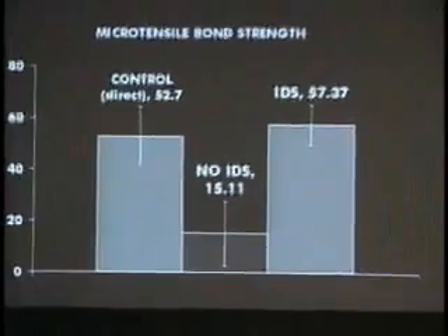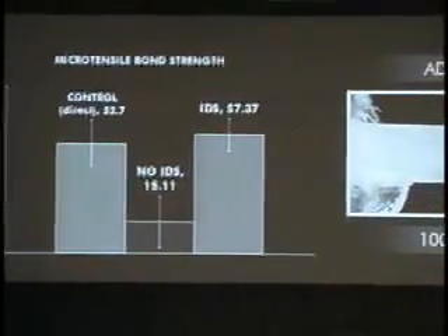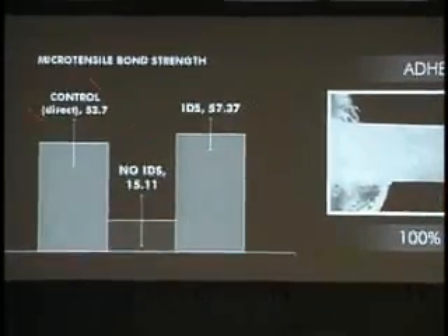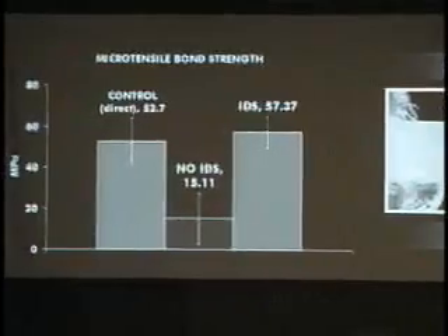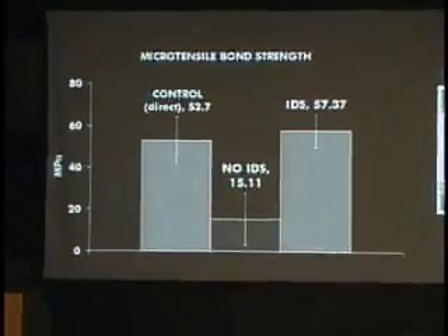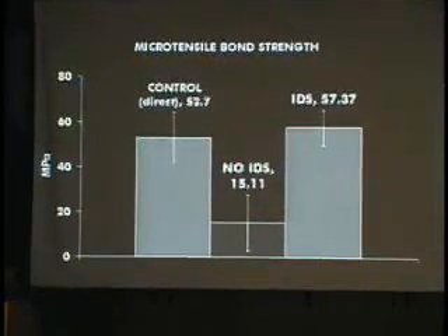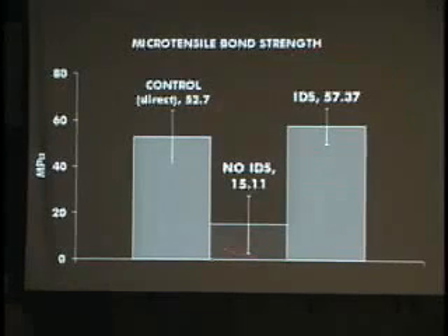And the force you need to break is between 0, if you have bad bonding, and 7 kilograms of force on this little 1 millimeter square sample. And the results are very, very interesting. We tested direct bonding, which is like you do when you do a direct composite. You cure the adhesive and you place the restoration immediately, versus indirect bonding without using immediate sealing or with immediate sealing. And I tell you the difference is huge.